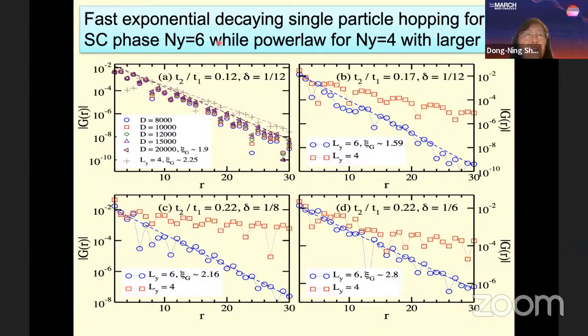At the same time, for this superconducting and CDW coexisting phase, we find the spin correlation always decays, and the electron Green's function always decays exponentially for the 6-leg ladder. But for the 4-leg ladder, the single particle correlation decays very slowly. This indicates that in the 4-leg ladder, that phase may have gapless nodes which make the electron single particle decay in a power law manner.